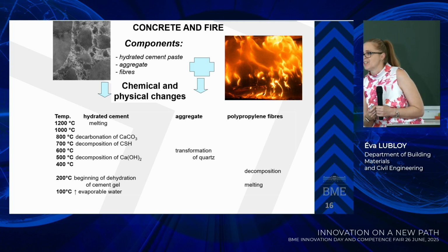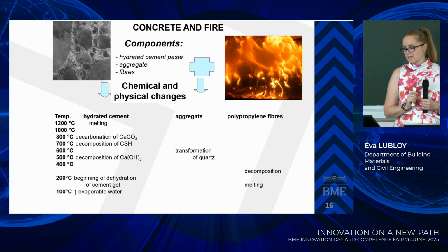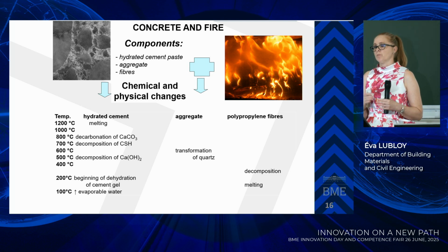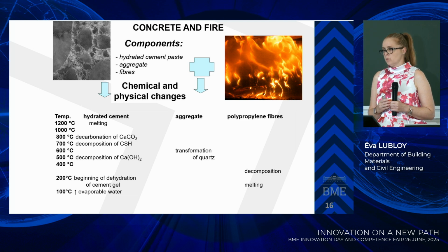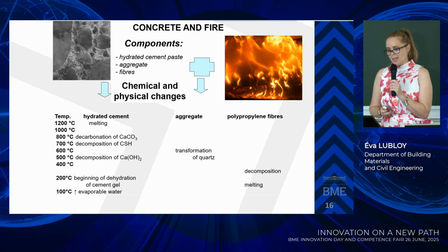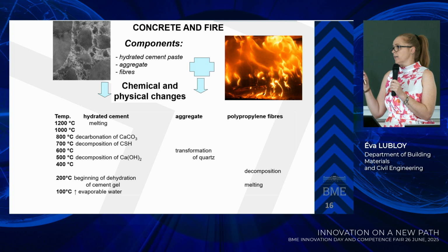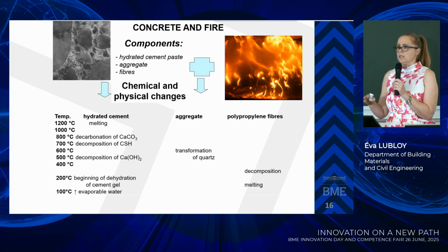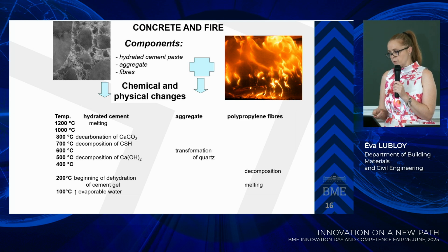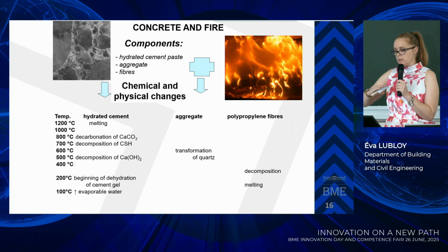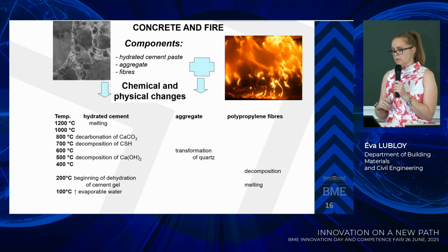I will not explain this picture because it is more chemistry, but it is important to know that hardened cement paste is the most important part of concrete. And we have two main components. The first is calcium hydroxide, and it decomposes after 500 degrees. And we have calcium silicate hydrates, and they decompose after 700 degrees. Calcium hydroxide is responsible for the bond characteristics, the bond of aggregate, the bond of reinforcement. And calcium silicate hydrates give the strength of the concrete. These are important things because by choosing a good cement type or good supplementary material, we can reduce the amount of calcium hydroxide and we can make better concrete.